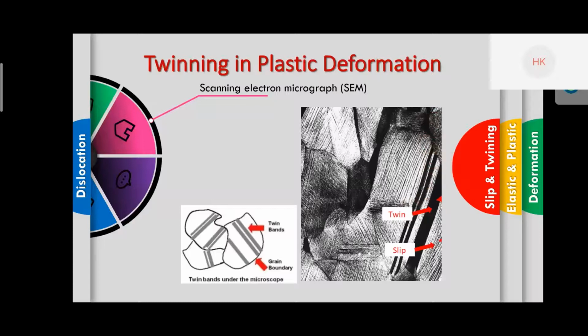Because of the deformation, we have slip and twinning. If we have a bigger grain boundary, the migration of the twinning deformation will go on longer, so it will weaken the metal. For the final product, we would like the metal to be strong, suited to the application. So to get a strong metal, we need to manipulate the grain boundary to make it smaller. Once we make it smaller, the distance or length of the slip or twin becomes shorter, so it will make a stronger metal. If the deformation is long, it will reduce the strength of the metal.